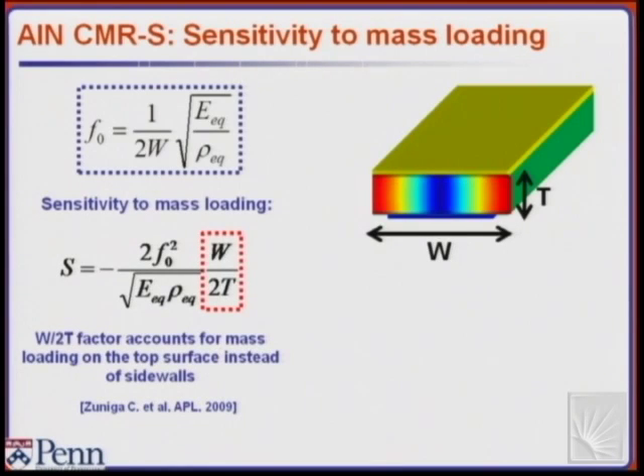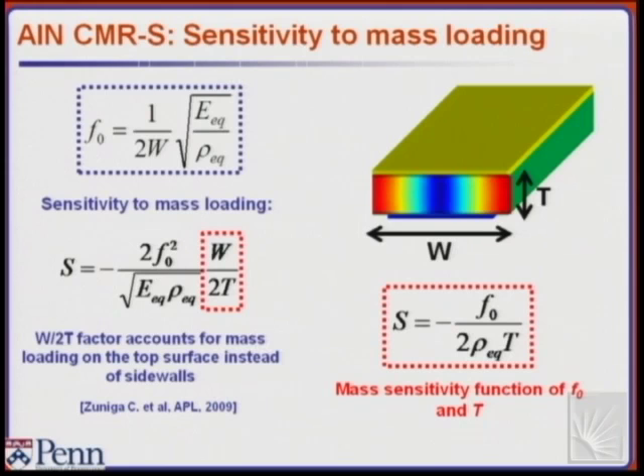It turns out that, given our geometry, that equation assumes that you're perturbing the direction of vibration. We can't do that in our resonator. We would have to put the absorbing layer on the thickness. We're better off putting it on top of the device, on the top surface, which turns out to be even more of an advantage, because the W over T ratio is generally greater than 1 for us. So the sensitivity of the device even goes up. And you end up with a sensitivity equation, if you express frequency as a function of W, that depends on frequency and is inversely proportional to thickness. So you probably already understood that if you make it thinner, the sensitivity will go up. If you make it higher frequency, the sensitivity will go up.